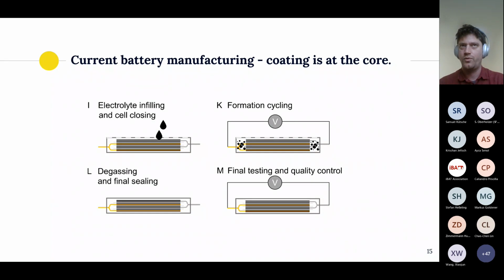And you cannot ship the cells quite yet. Typically, the solid electrolyte interface needs to be formed. So you do some formation cycling, some quality testing, depending on the cell format. You degas the byproducts of the formation process, and then and only then you're finished. So it's a very complex process in which many companies and stakeholders are involved.